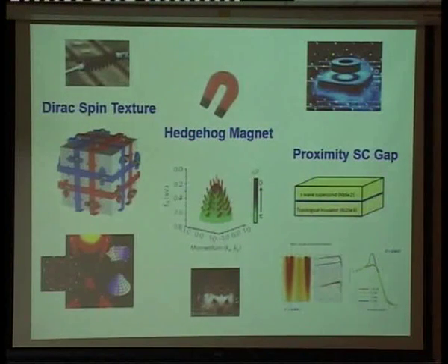This result is unpublished. What does manganese do? Does it replace, or is it staying on the top? In some cases, sometimes it even clusters. But what is interesting, no matter what it does, homogeneous or inhomogeneous, the surface states develop this texture. But there is a global net out-of-plane component. Now you can see that your surface Fermi surface is spin polarized, there is a net moment. And that's independent of how manganese is distributed in the sample.